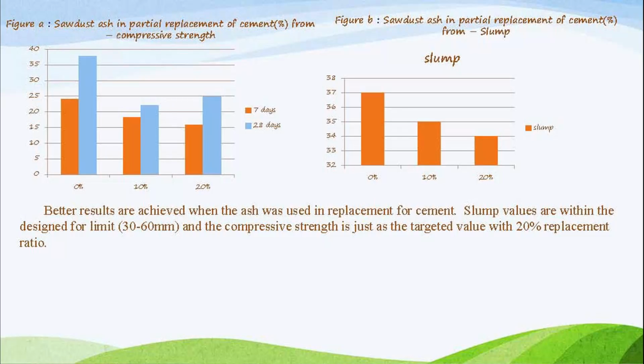If we look at the result, we find the compressive strength decreases for sawdust. If you are using sawdust about 10%, then it increases when we use a percentage of sawdust of 20%. The workability or the slump test of samples using sawdust decreases about 20%. Then if we increase the percentage of sawdust used in replacement of cement, the workability also decreases. Better results are achieved when the ash was used in replacement of cement.